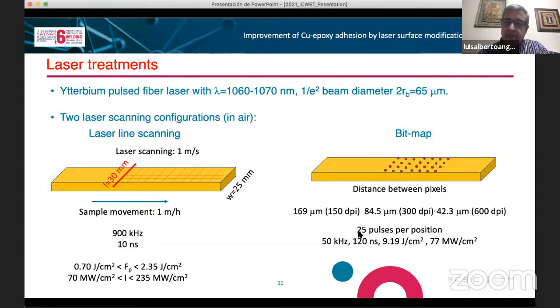In each position, we have applied 25 pulses, and in this case, we have been working with 120 nanoseconds pulse width. We have been using an irradiance value close to the lowest one in the previous case.